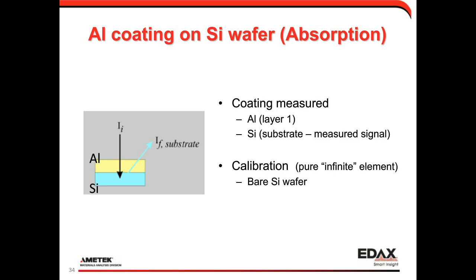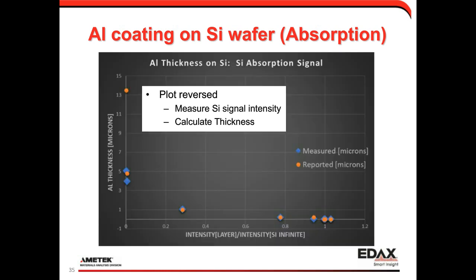So this is the situation that we're measuring here. We've got aluminum on a silicon substrate, and we're measuring the silicon signal coming through. In this particular case, as I mentioned before, we're not calibrating against any coating standard at all. I'm putting in a bare silicon wafer, calling that 0 microns of aluminum coating, making a measurement on that, and getting the calibration coefficient off of that. And here are the results for this plot.